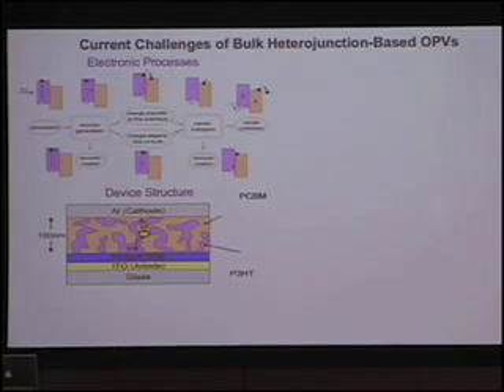Okay, so another way to solve this problem is to create a so-called bulk heterojunction. Instead of just having a two-layer device with a junction here, you create it through phase separation. When you anneal two different incompatible materials, you create this phase separation. So you form multiple junctions. So you have a much shorter distance for the exciton to find the interface to dissociate, find their corresponding conducting paths, and be collected.